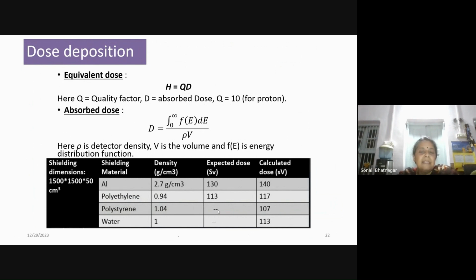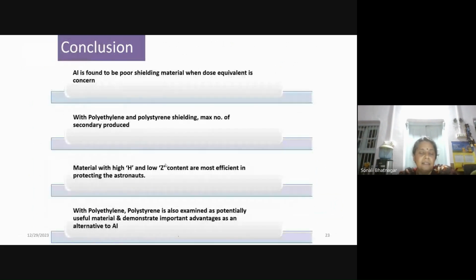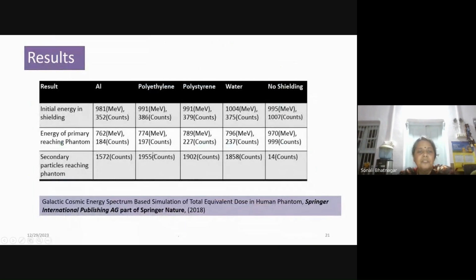So this is basically telling us that these materials, both polyethylene and polystyrene, the organic scintillator, they have the maximum number of secondaries produced. Now this is also one factor that you should appreciate here, because these two materials were able to break the primary particle into secondaries, which are less harmful, so a much better shielding was there, because the primary particle is the harmful thing. It should not be absorbed by the human body. So even if the secondaries are absorbed, their energy is already reduced, so it will not be a problem.